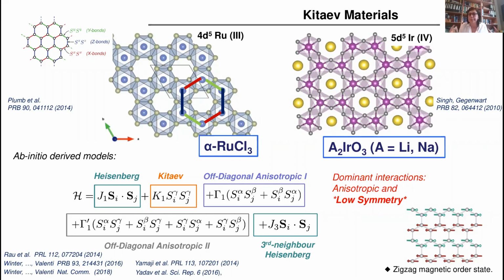However, these are not perfect. You don't have all the perfect conditions you would need in order to have only Kitaev surviving. You do also get some small nearest-neighbor Heisenberg interactions, as well as other off-diagonal anisotropic contributions. These type of interactions are responsible for the fact that the ground state of these systems is not a spin liquid, but an ordered, long-range ordered magnetic state in a zigzag fashion.